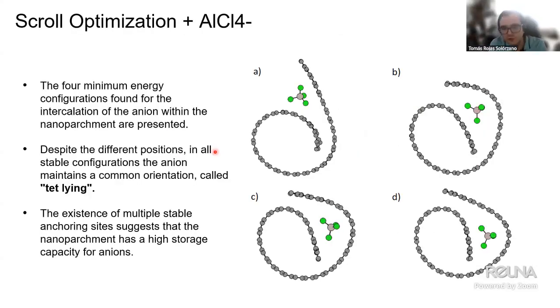We found 4 configurations that were really stable, meaning that for the sizes of the scrolls that we were able to test, we found 3 configurations that more or less reduced to 3, because these last 2 were very close to each other in energy and position. But we found out that the scroll adapts really well to the presence of the ion, meaning that if it is close to the mouth, it will open out and keep it in one place, meaning the molecule won't easily just leave, just based on the interaction between them. But it will stay there without easily moving out. Whereas if you move it close to the other end, it will try to move it and keep it in as close to the middle part as possible. But always, in these cases, maintaining the tetrahedral configuration of the absorption.